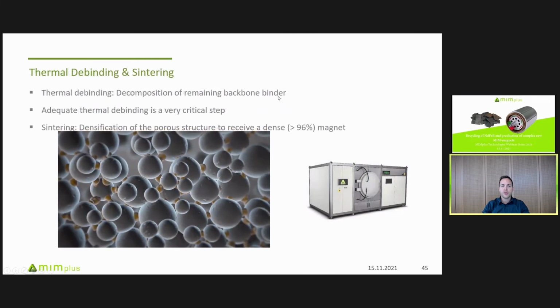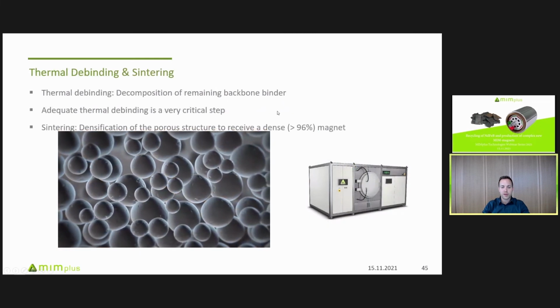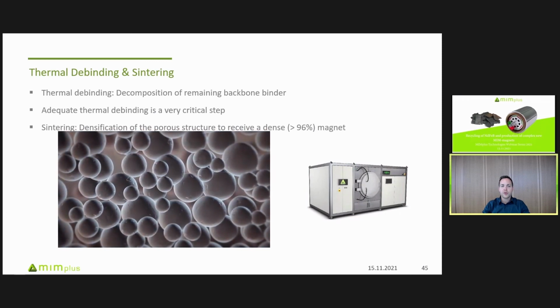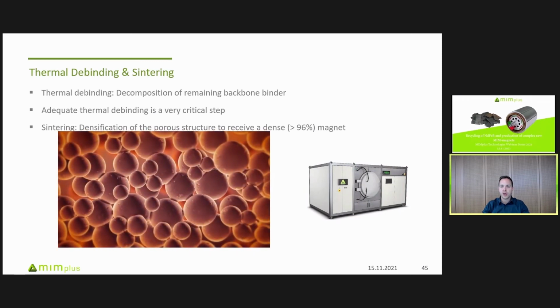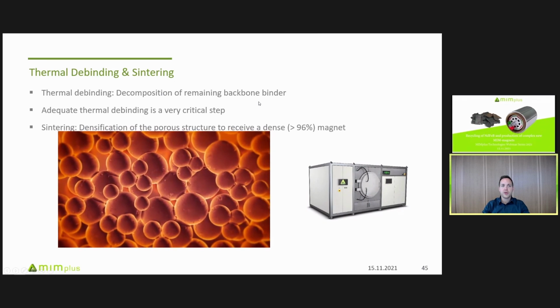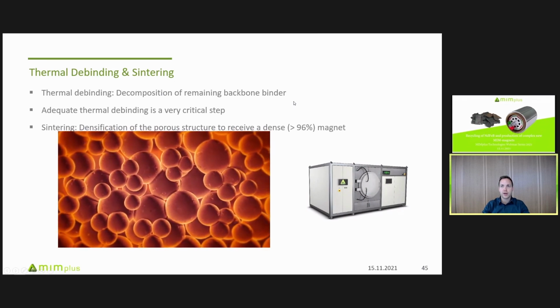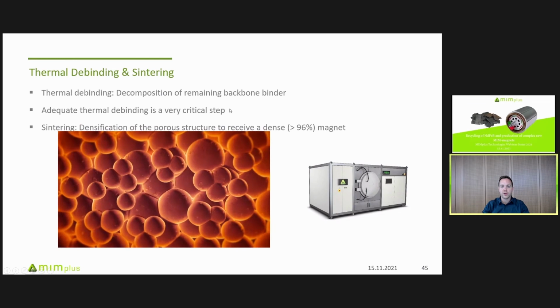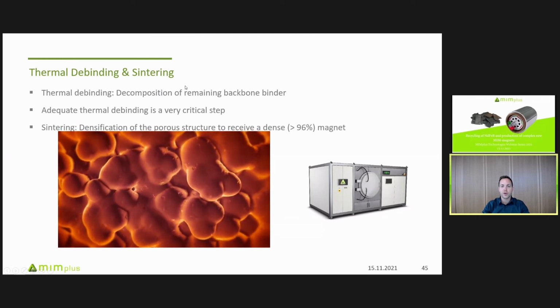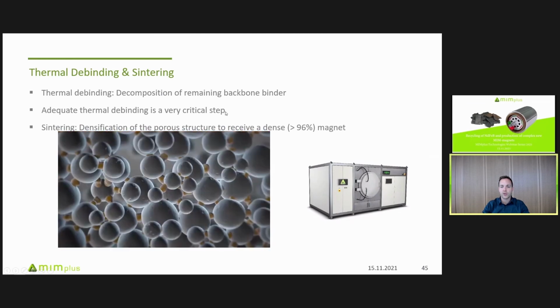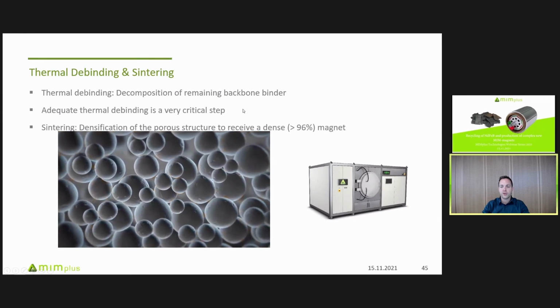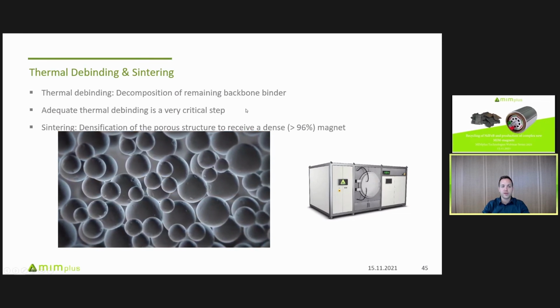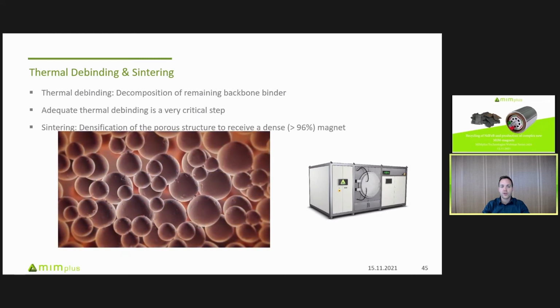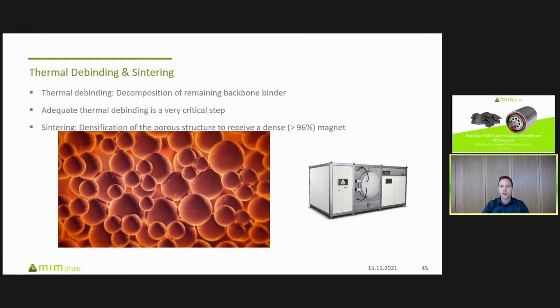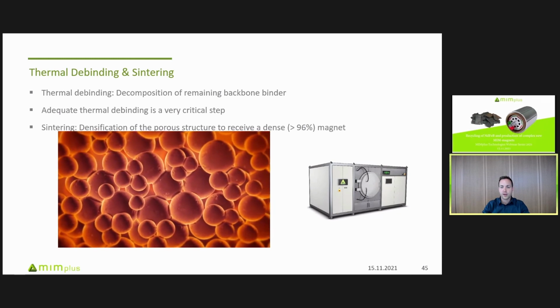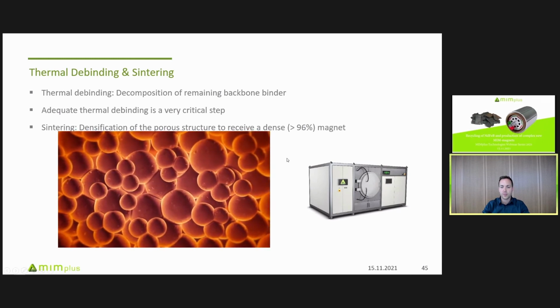The thermal debinding and sintering step is one of the main critical steps in the whole process chain, because here you decompose the remaining backbone binder in the open porous structure. And there you need adequate thermal debinding procedures to guarantee that you don't have any reaction of the decomposition products with the highly reactive neodymium iron boron powder. And then after you deal with that, the sintering step follows, which is the densification of the porous structure to a 100% metallic and dense permanent magnet.